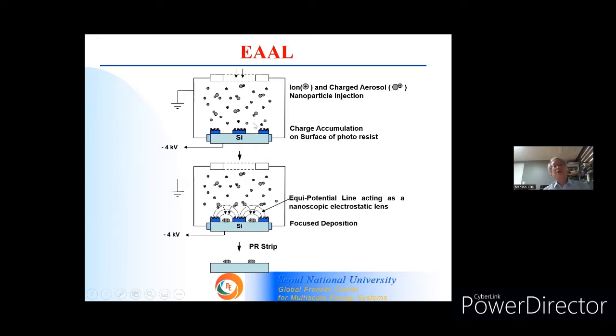And then accumulation of ions will modify originally almost flat equipotential plane into convex shaped equipotential plane. Since charged particle should move in a direction perpendicular to the equipotential surface, this charged particle should be focused. It's like an optical lens that can focus light. Our ion-induced electrostatic lens can focus charged material.